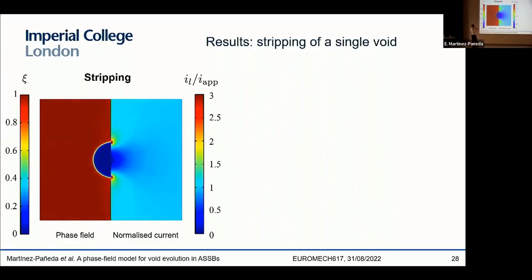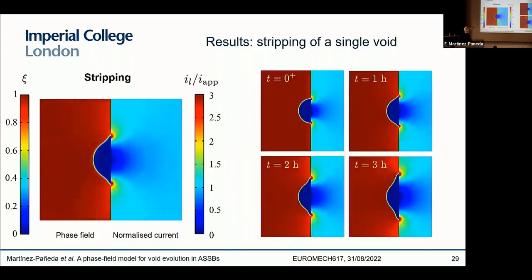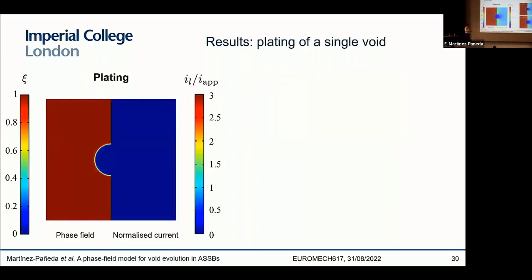And you can see basically that you get what you expect from the experiment, right? So you're having stripping, so your void is growing mostly along the interface. And then you see that you generate those current hotspots, those localized regions of high current near the void edges. And yeah, you can see it here. Again, as you see in those experiments of Peter Bruce, as you do stripping, you see how the void evolves mostly along the interface, and how you get this localized current there, which eventually is going to lead to the nucleation of dendrite.